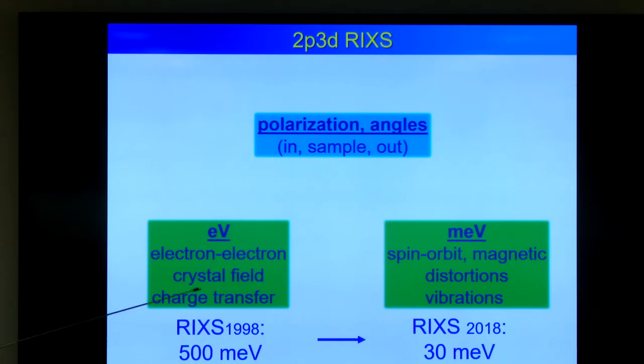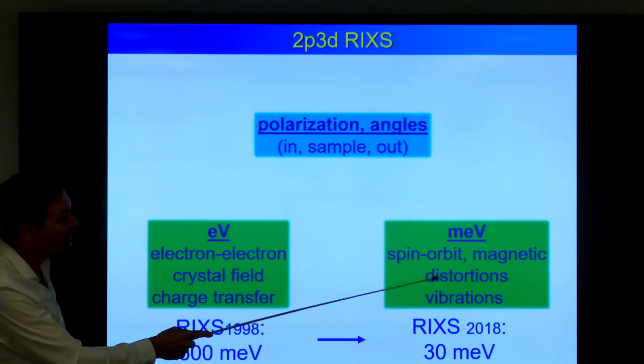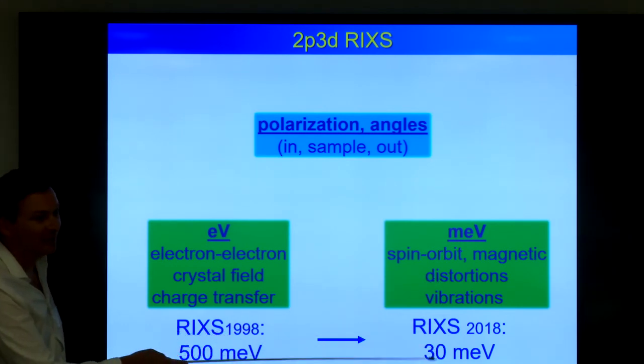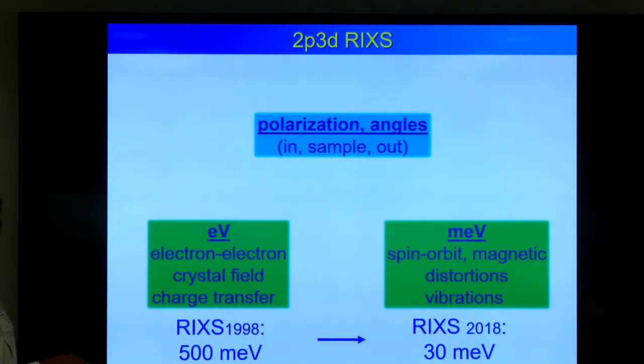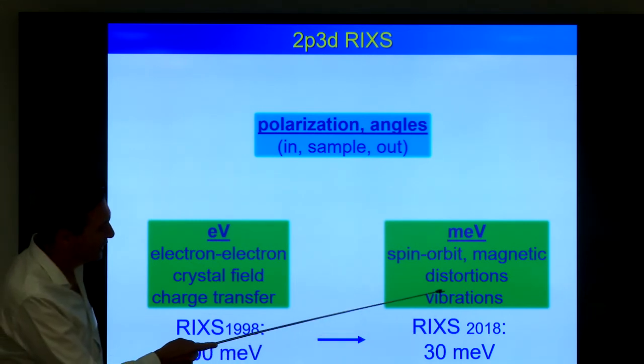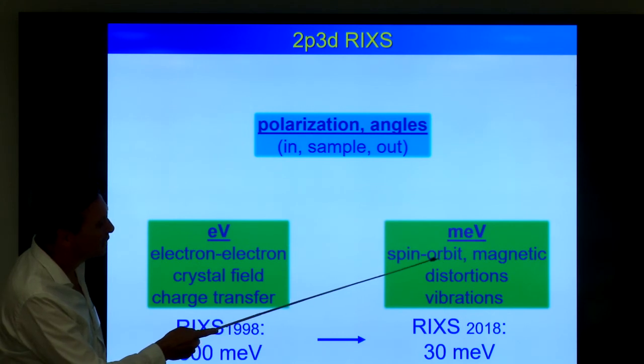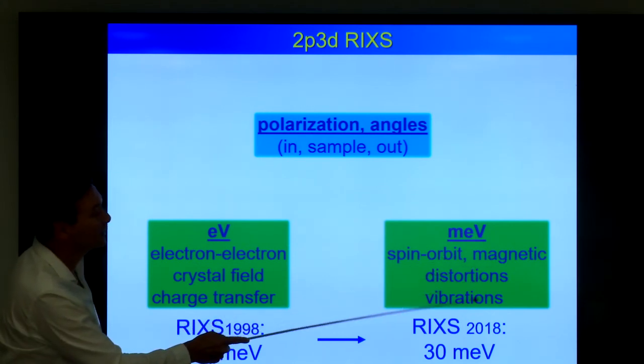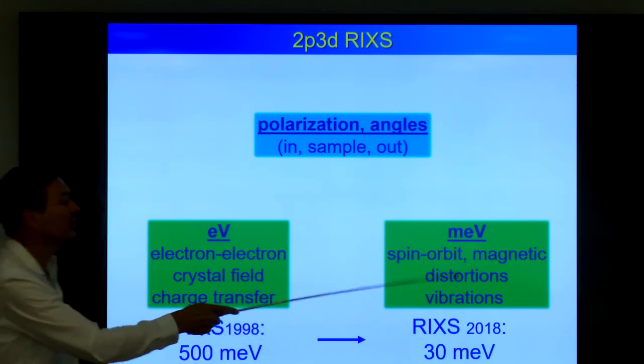With X-ray absorption, you are in the electron volt range, so you can study electron-electron interactions, crystal field effects, charge transfer effects, or chemical bonding effects, and screening effects. So that's typically done with X-ray absorption. But now we can go to millielectron volts. So I put 30, but nowadays I think ESRF is 25, and it'll be better maybe soon. But let's say 30, you can study spin-orbit excitations, magnetic excitations, distortions, and vibrations. So you go to a completely new set of